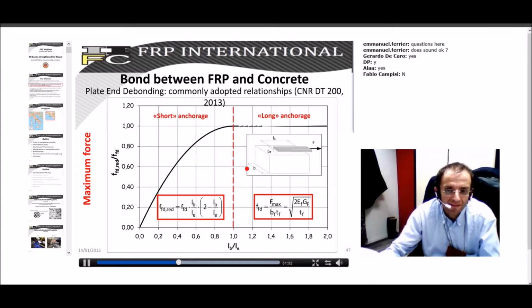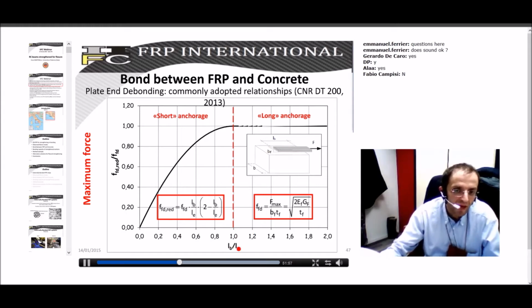Here you can see a ratio diagram explaining how the force, or if you want, the corresponding strength which can be applied to an FRP strip glued on concrete, divided by the maximum one, FD, depends on the bonding length. So if I reduce this bonding length below LE, I have a reduction, which can be approximately described this way. If I have a bonding length which is at least LE, I have a constant value of FD, which is derived from F max, so it is this 2 EF GF divided by TF.